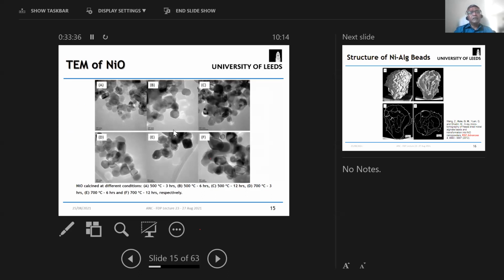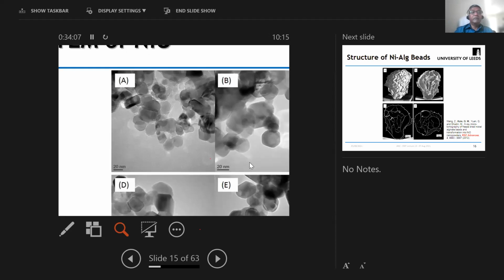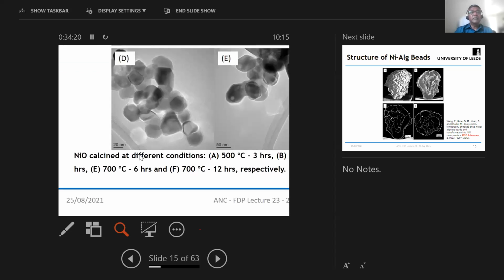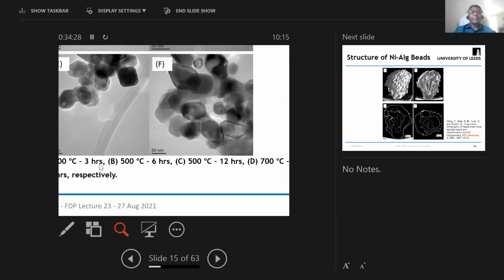So these are bigger particles, and therefore they are appearing dark on the TEM images as well, because they become less transparent, and therefore they don't show the lattice planes. Whereas here, if you zoom in, you will be able to see the lattice planes, particularly in this sample A, which is typically, let me see on the scale, about 20 to 30 nanometers. This is a 20 nanometer marker here. And you can see that it's about 20 to 30 nanometer in size, whereas here the particles are much bigger. For example, when you calcine at 700 for 12 hours, the particles become really big. That's a 50 nanometer marker. So it's about 100 nanometer in diameter from corner to corner, I suppose.